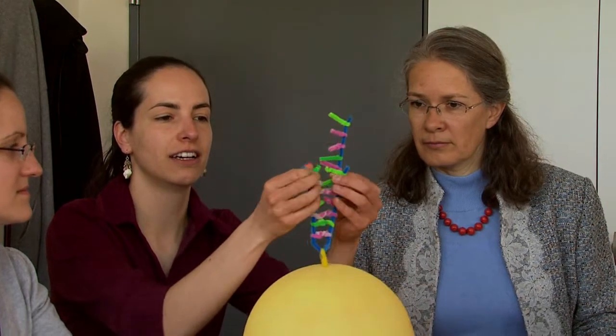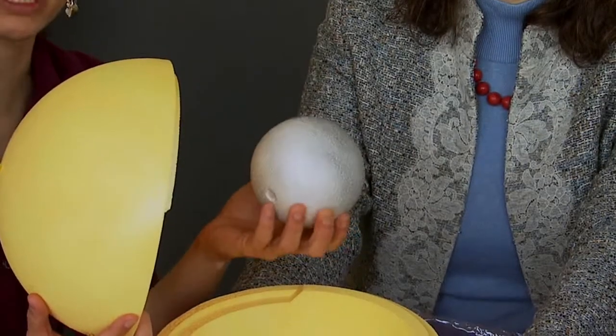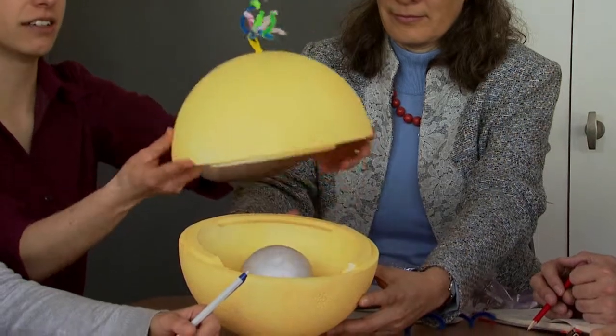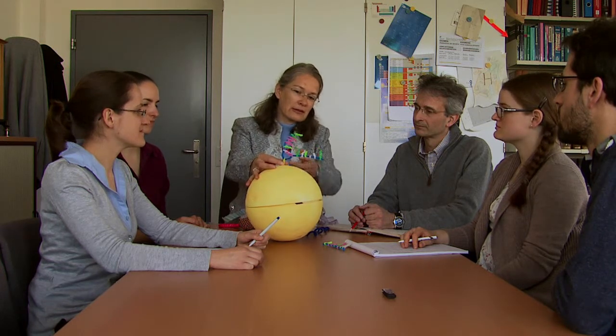The nanocontainers obtained were all successfully used to encapsulate silver in the form of either silver nitrate or silver nanoparticles. However, the system of choice is the silica material. The micro-gel method allowed incorporation of up to one silver nanoparticle into one silica capsule — the researchers term these systems nanorattles. Since those nanorattles showed good biocompatibility and antimicrobial properties, they might be the best candidate for medical applications.